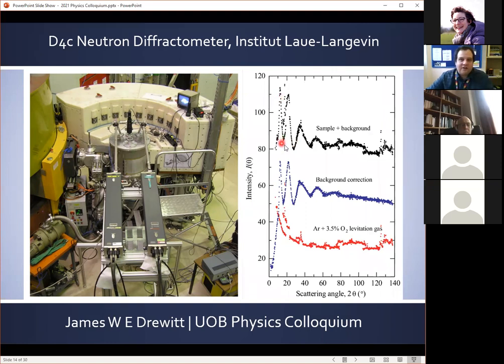So here I show an example of the scattering intensity during a levitation experiment at D4C, and we can see that, as for X-ray diffraction, our intensity is more or less what you see is what you get for a liquid structure factor measurement, although the levitation gas gives rise to slightly higher background due to the higher scattering length of argon for neutrons.